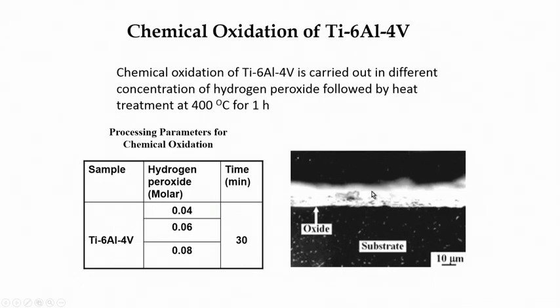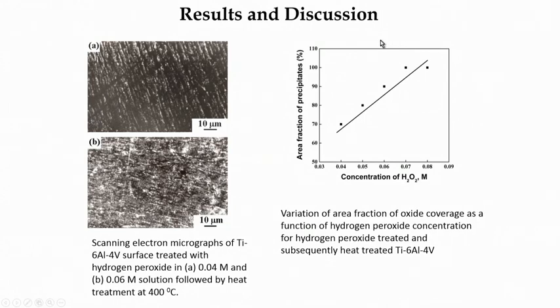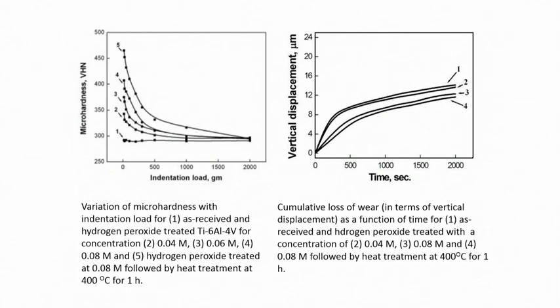This oxide was mainly anatase in nature, and if you see the oxide scale properly, you will find very fine oxides present. If you see the morphology, you will find very thin, fine, nano-sized precipitates on the surface. As you go on increasing the hydrogen peroxide concentration, the area fraction of the particles also increases. So, coverage depends on how much time or how much percentage of hydrogen peroxide you are using for the oxidation purpose.